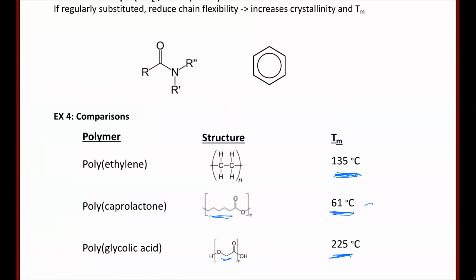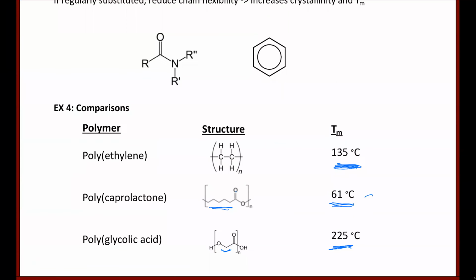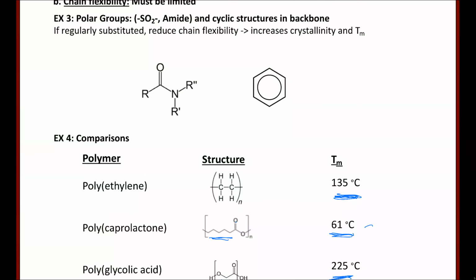So give me an example. What is a pendant group that you've got in there? Well, it says bulky or rigid groups. Okay, what is a bulky rigid group? I was just thinking of like a ring structure. Okay, yeah, like a phenyl group, right? So if it's got those bulky groups, then yeah, that can increase the melting temperature. If it's something like a long chain, which is carbons extended out, then your chains won't get close enough together to form crystalline regions, or they won't form many of them. That's bulky and flexible.